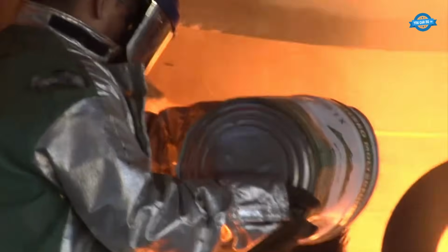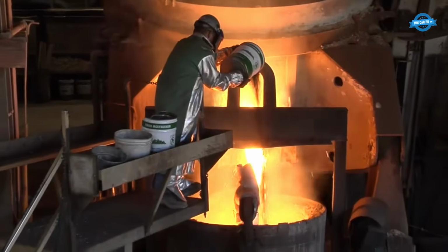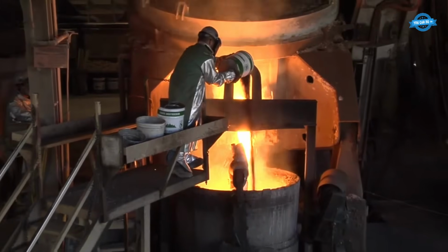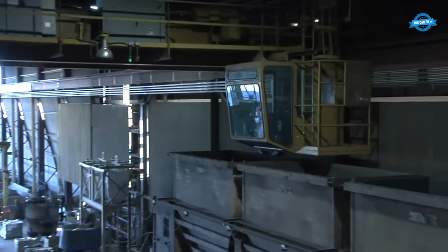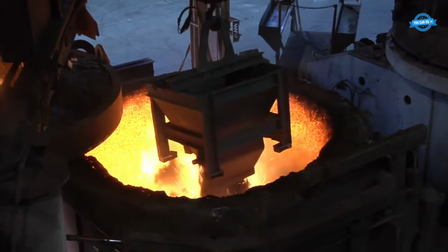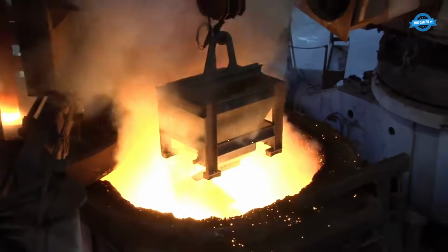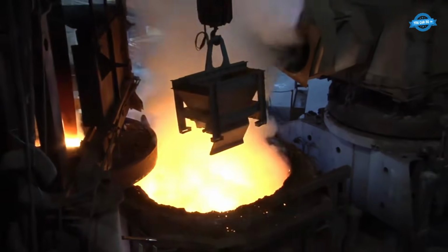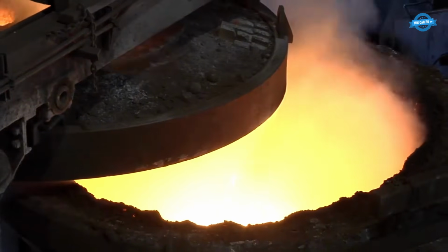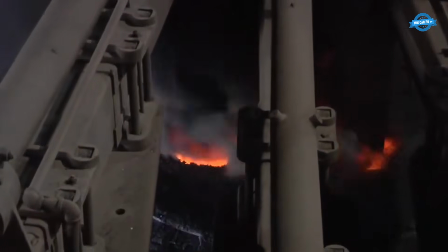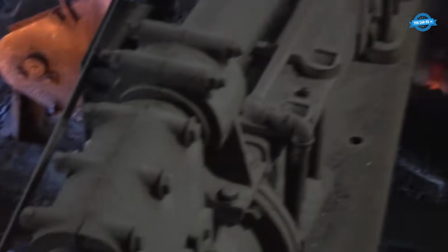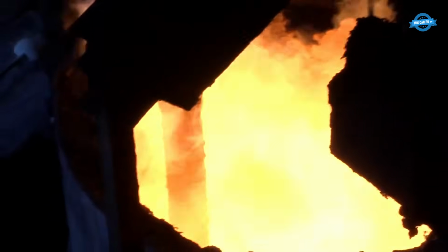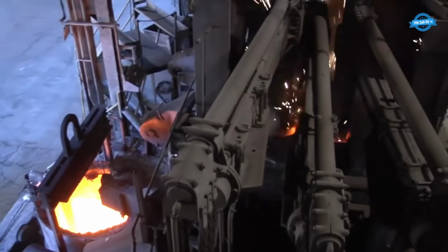The roof opens, scrap drops in, and graphite electrodes strike arcs through the metal itself. Low voltage protects the roof and walls at first. Once the electrodes bore into the charge, voltage rises, arcs lengthen, and power surges. Oxygen burners cut and combust steel, adding chemical heat. Alloys and slag materials enter mid-heat, while samples verify chemistry.